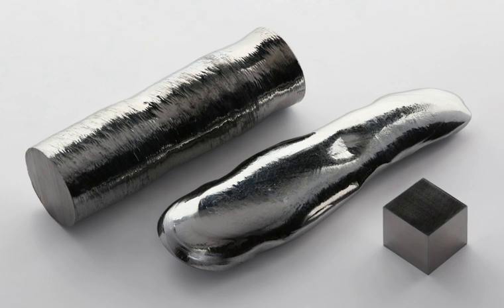Total world production is between 40 and 50 tons per year. The main producers are in Chile, the United States, Peru, and Poland. Recycling of used Pt-Re catalyst and special alloys allows the recovery of another 10 tons per year. Prices for the metal rose rapidly in early 2008, from $1,000 to $2,000 per kilogram in 2003 to 2006 to over $10,000 in February 2008. The metal form is prepared by reducing ammonium perrhenate with hydrogen at high temperatures.